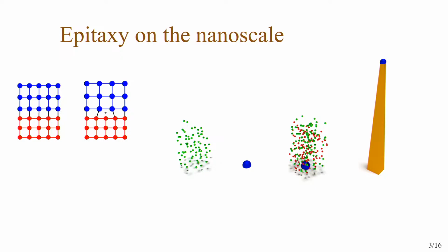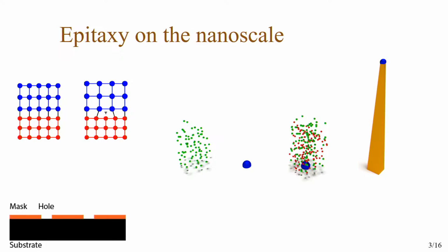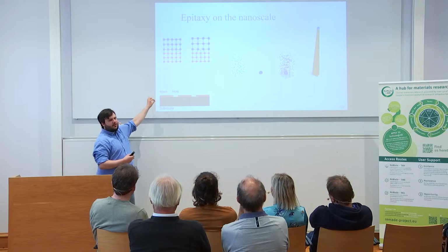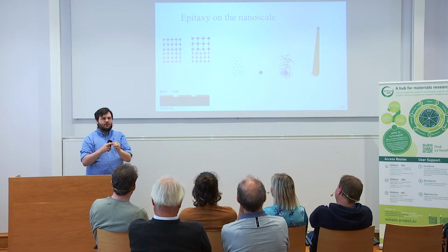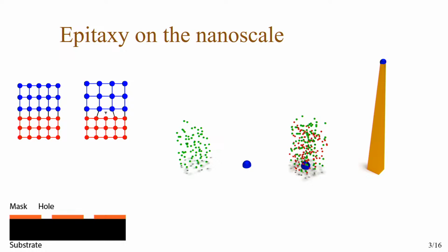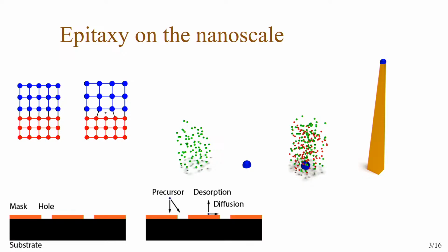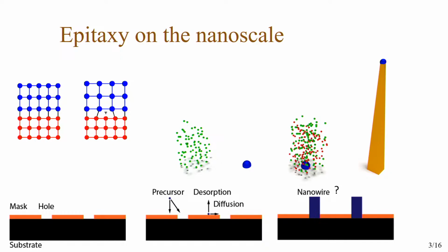Another way to do it, which will actually be the main focus of this talk, is so-called selective area epitaxy. So I have the substrate that I grow on, and I have a small mask layer on top where I make nanoholes. And in these nanoholes, I can make the material selectively grow inside. So then I can also limit the area between the material I grow and the substrate to help reduce defect formation. Again, I supply the gases that can go around the surface, and it can also lead to a nanowire growing. But the question mark there is because I tried this in my PhD to grow nanowires, and I failed spectacularly. That has led to my last 5 years of research. But I'll get into that as well.